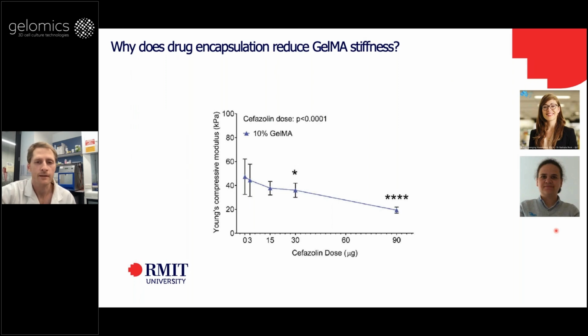They were adding cefazolin, which is an antibacterial drug, to GelMA, and seeing a reduction in stiffness, but they didn't have a satisfying explanation as to why. So we started working together, and I did some in situ photorheology experiments to try and understand what was going on. How could this drug molecule be influencing the cross-link density or the stiffness of the hydrogel?